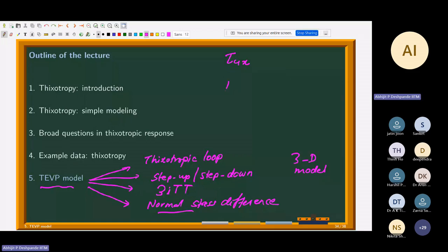And so normal stresses tau xx, tau yy, and tau zz in the material will also be present, and their differences are what is being captured when we are trying to look at this. This is all due to the elasticity in the material. So normal stress differences are a very good indicator of the importance of elasticity in the material.